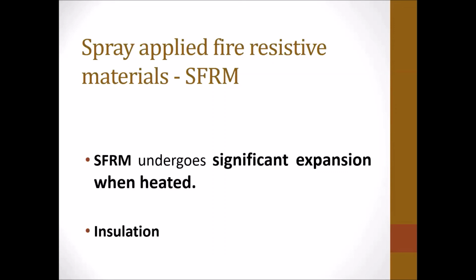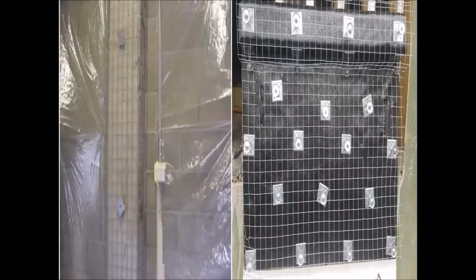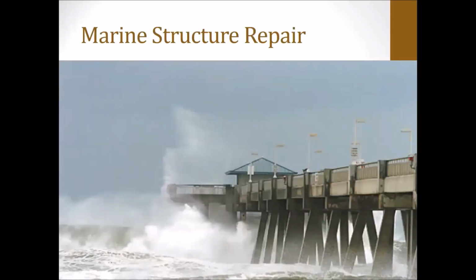We have to protect the structure, or enhance the durability of the structure. We use fibers, and to protect the fibers from the fire we have to use fireproofing materials as well. Once we install the carbon fiber or glass fiber, the application of the fire resistive material is very difficult. So then we have to use glue, epoxy glue pins. Then around 2-inch thick insulation materials we have to spray on top of the carbon fiber.